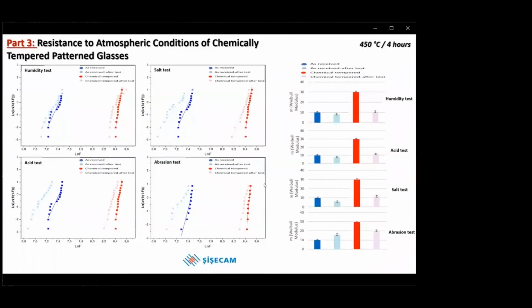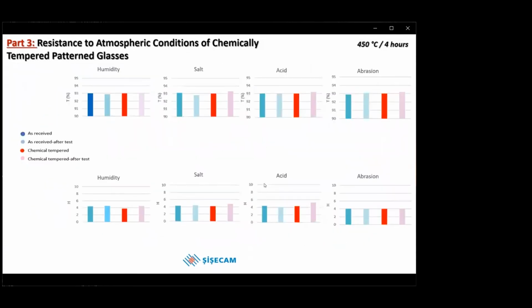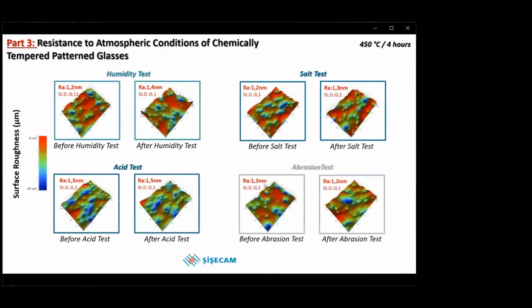Weibull diagrams were drawn using the values obtained from the ring-on-ring test. It was observed that the Weibull modulus increased after chemical tempering. It seemed that the Weibull modulus of chemical tempered glass samples decreases after the test with atmospheric conditions. As a result, it has been determined that the chemical tempered glasses are more reliable than as-received glass in terms of resistance to atmospheric conditions. When the optical transmittance and haze values before and after chemical tempering were examined, no significant difference was observed in the transmittance values of the glass samples. When we look at the surface roughness values, it has been observed that the atmospheric conditions don't significantly change the surface roughness of the chemically tempered glasses.